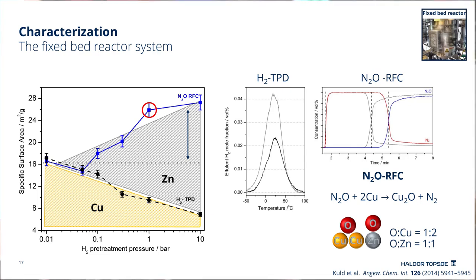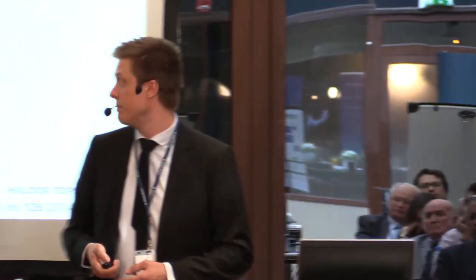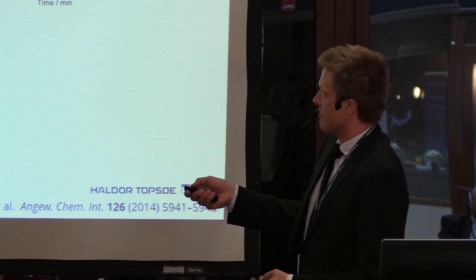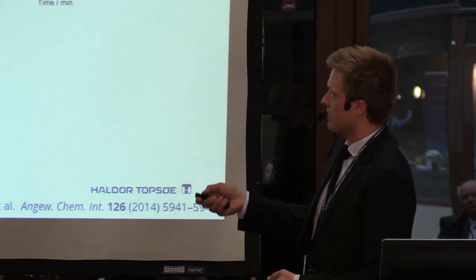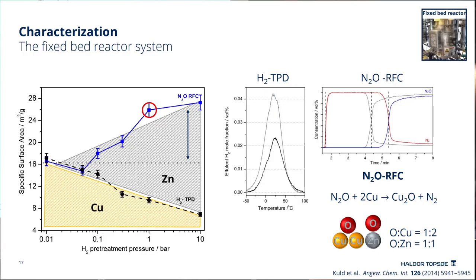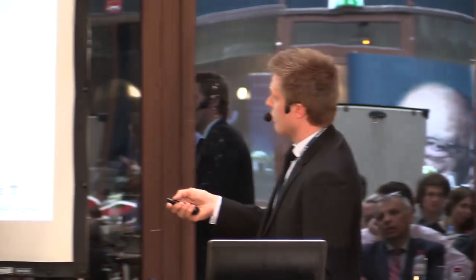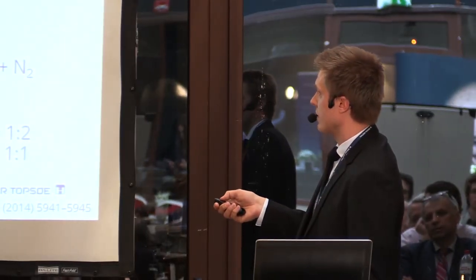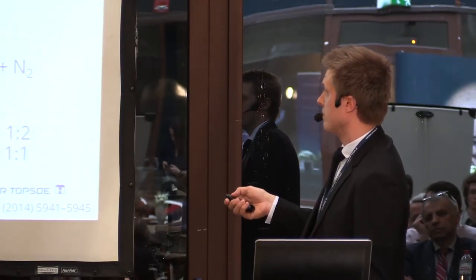So how can we interpret this? This actually fits exactly with zinc being incorporated into the surface of the particles. So you can say, why this factor of two? Why is the area increasing? And in order to explain that, we really need to go into the details of how this area is derived, because it's based on a stoichiometry. So in this nitrous oxide measurement, you have one nitrous oxide molecule reacting with two copper atoms to form a copper oxide and a nitrogen.